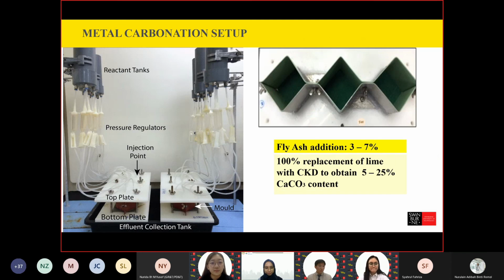This diagram shows the metal carbonation setup. A mixture of CKD, fly ash, and sand is compressed in the mold and placed between two plaques for the metal carbonation process. The bicarbonate solution is introduced through various injection points. The percentage of fly ash addition used was 3 to 7%. CKD is used to replace lime to achieve 5 to 25% of CaCO3 precipitation content.